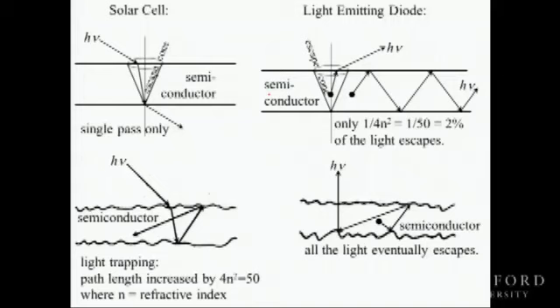Let me illustrate it here by comparing the solar cell with the light-emitting diode. This escape cone is just part of normal optics. If you're a diver, you know that at a certain angle under the water, you see the reflection of the sand. You can't see out. This is a very severe problem in semiconductors because the refractive index is 3.5, and so this angle is only about 16 degrees. Only a tiny amount of the light is able to escape.